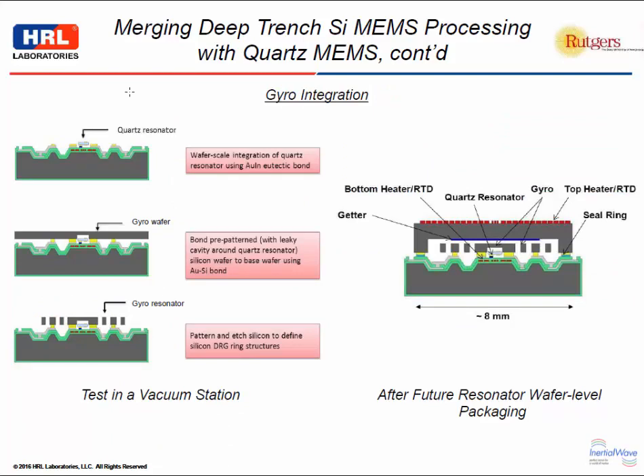So finally, the last step is then merging the gyro integration. So we go back to put on our silicon MEMS hat, and now we add a 111 heavily boron doped silicon wafer to the top of the structure. We bond it to the existing gold pads with a gold-to-gold thermal compression bond, and then etch with deep RIE the gyro structure, and that leaves us with a wafer then that we can test in the vacuum station.